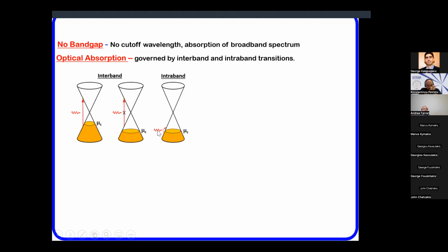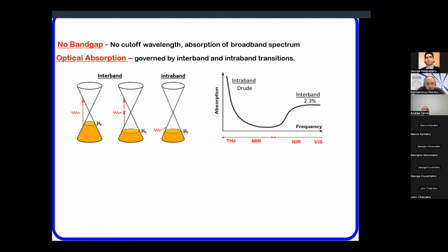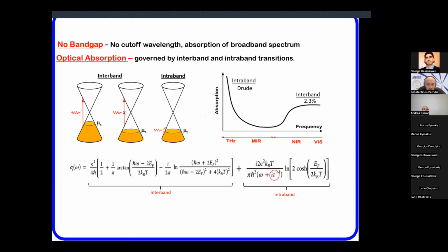However, what's important to notice is that in real graphene, not ideal graphene, there are lots of processes that create these intra-band transitions, no matter what wavelength you have. And this is mostly due to defects and wrinkles and this sort of thing. So ideally, each piece of graphene absorbs 2.3%, and you will go exactly to 0, but you don't because of this intra-band transition. I will not discuss today what happens at extremely long wavelength, extremely low energy. So this is just about the only equation I'm going to show.